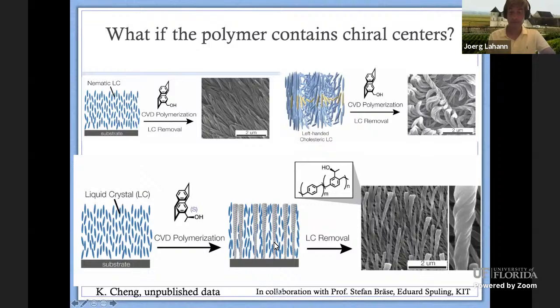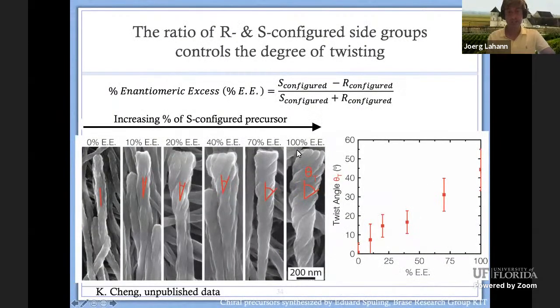So that's really exciting. And so here, as we change the EE, so basically we change the mixture of the two enantiomers in the paracyclophane that we create, we get different amounts of pitch. So the pitch can be tailored, can be increased or decreased, as a function of the ratio of the two enantiomers that we use. And also the twist angle changes as well here and steadily increases as the chiral paracyclophane becomes more and more pure. Okay, so there's more work to come here, and we have done a little bit more. We can actually induce chirality with those systems as well, which is interesting.